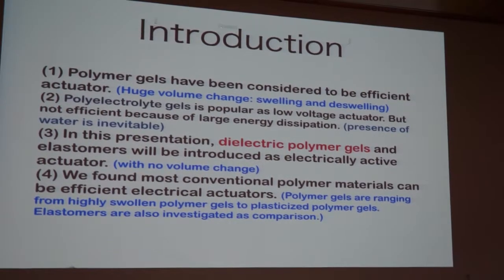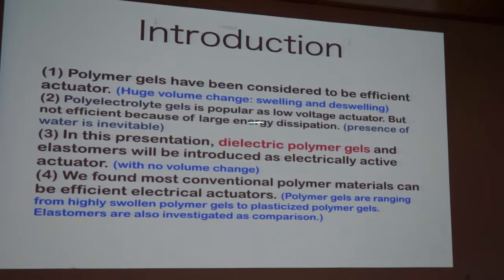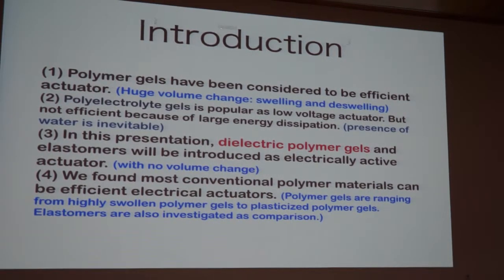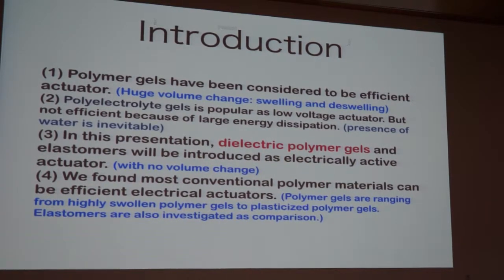But in the case of polyelectrolyte gels, which contain some amount of water, they can be actuated at very low voltage, for instance, 2 volts or 3 volts is usually enough. But at high voltage, electrolysis occurs on the electrode, and that is inconvenient. And usually, the presence of water is inevitable. That is also inconvenient. And particularly, a large current is observed, and energy dissipation is huge. So for practical application, this also has some difficulties. That's the point where I changed my viewpoint to dielectric polymer gels.